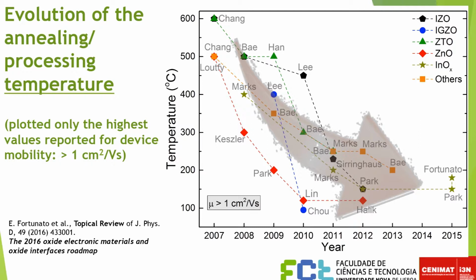the dependence over the last years. This is the tendency. Here we have the temperature as a function of the years for TFTs using different metal oxides. We don't care about which. But what is important to see here is that the first TFTs that were produced using a solution approach, a chemistry-based approach, if you want, the temperatures needed were quite high, around 500 and even 600 degrees. But nowadays it is possible to use a very low final deposition temperature. So we can use, as I mentioned before, polymeric or even paper substrates. This is the temperature process.